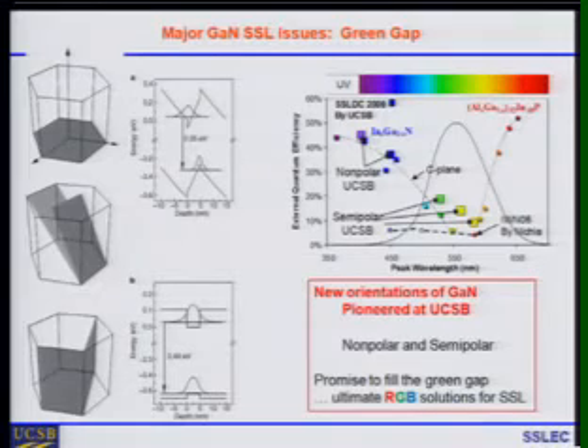Another issue that was pioneered at UCSB is new orientations of gallium nitride that we call nonpolar and semipolar. And we've already shown with our data at UCSB that we're able to fill this poor efficiency gap in the green region. And we're very optimistic with continued science and engineering that we can fill the green gap. And so this is another area we're looking at.